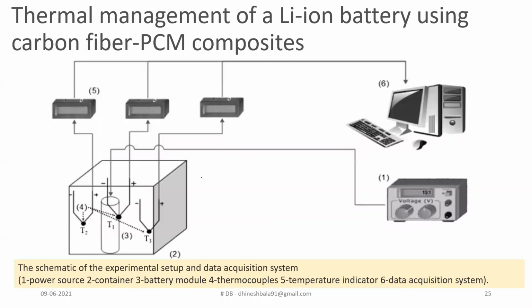And in the study, they have considered a small chamber, and in between that they have poured the paraffin wax and placed the battery inside, and along with that they have connected the charging and discharge unit and tried to charge and discharge it at different rates. Because of charging and discharging, the battery would get heated, and they have placed thermocouples closer to the battery and the phase change material and tried to monitor the temperature impact with respect to the charging and discharging cycle. So this is one simple study they have carried out.